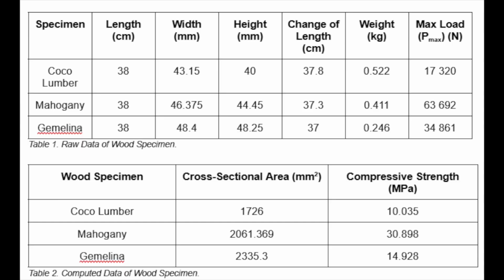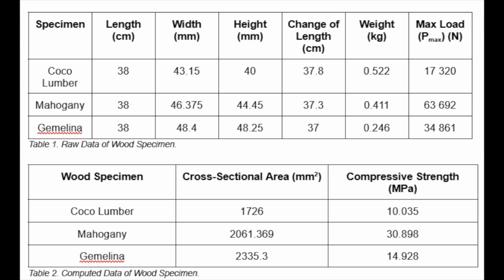Among the 3 wood specimens tested, mahogany exhibited the highest compressive strength at 30.898 megapascal, followed by Gmelina at 14.928 megapascal and cocoa lumber at 10.035 megapascal. These results show that mahogany can withstand the greatest compressive force before failure, confirming its reliability for structural application.